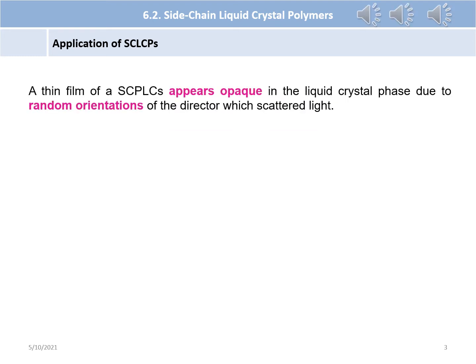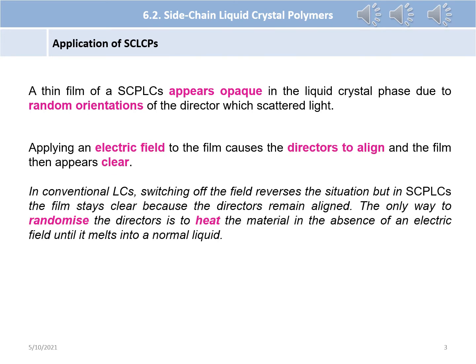A thin film of a side-chain polymer liquid crystal appears opaque in the liquid crystal phase due to random orientations of the director, which scatter light. Applying an electric field to the film causes the directors to align and the film then appears clear. In conventional liquid crystals, switching off the field reverses the situation, but in side-chain polymer liquid crystals, the film stays clear because the directors remain aligned. The only way to randomize the directors is to heat the material in the absence of an electric field until it melts into a normal liquid.